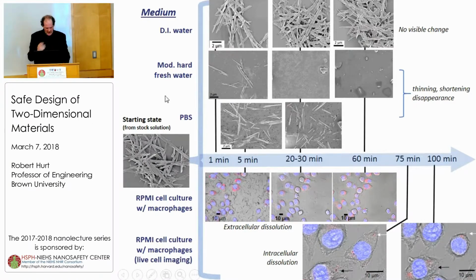And this is a kind of morphology diagram, starting with the nanoribbons at the beginning, and then in DI water, where we see no change really over the entire course of the experiment. In EPA moderately hard freshwater, an environmental simulant, we see the gradual dissolution of these ribbons. And that's because this water has calcium and magnesium in it, which provides some buffering capacity and prevents it from reaching equilibrium.